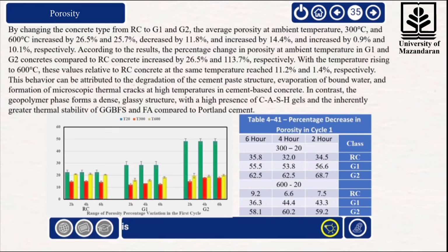Porosity. This diagram shows the range of porosity variations during the first cycle for the 3 types of concrete at 20, 300, and 600 degrees Celsius. Overall, porosity values varied significantly with the type of concrete, from RC to G1 to G2. Results indicated that at ambient temperature, the porosity of G1 and G2 was 26.5% and 113.7% higher, respectively, compared to RC. However, at 600 degrees Celsius, these differences decreased to 11.2% and 1.4%, respectively.